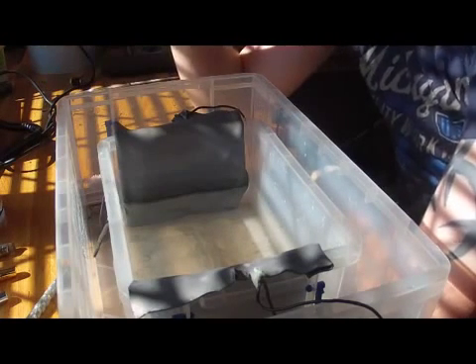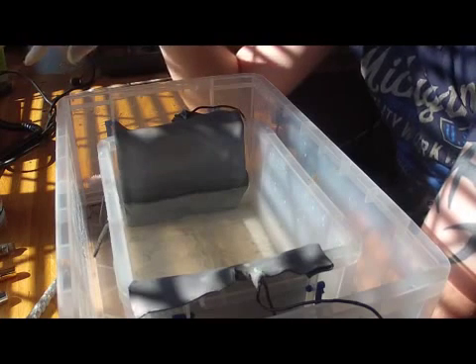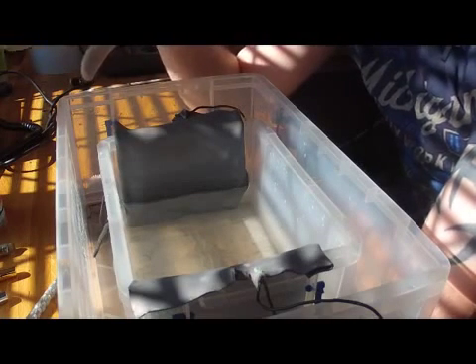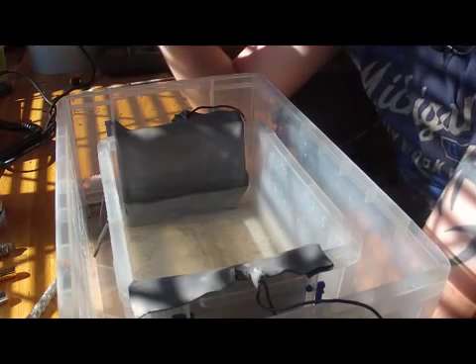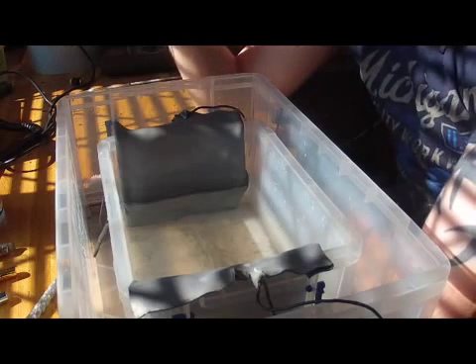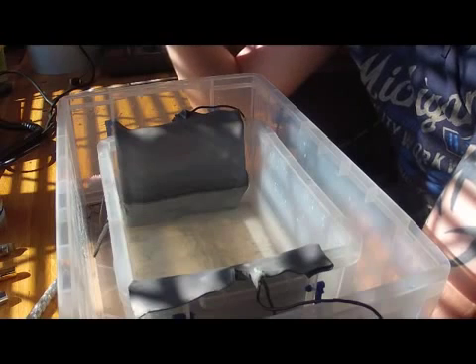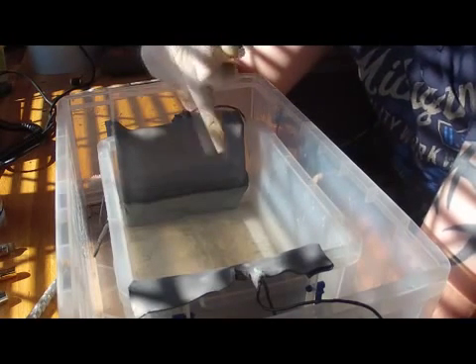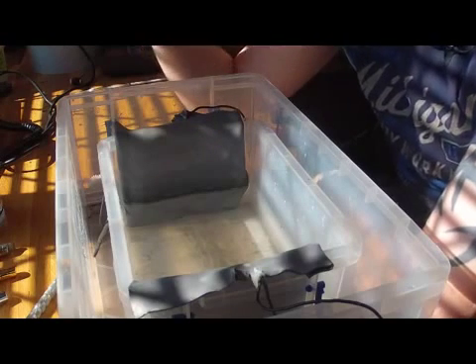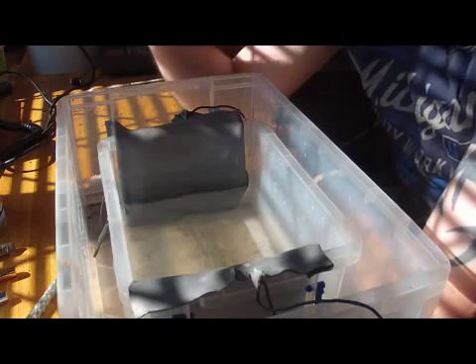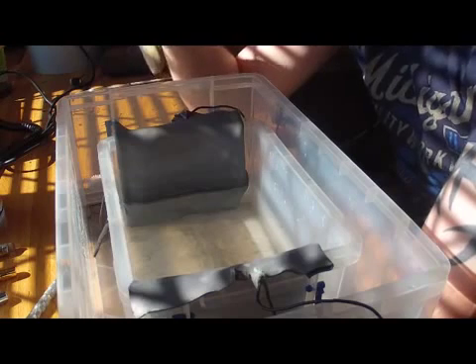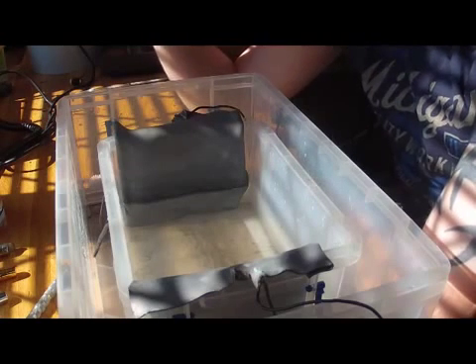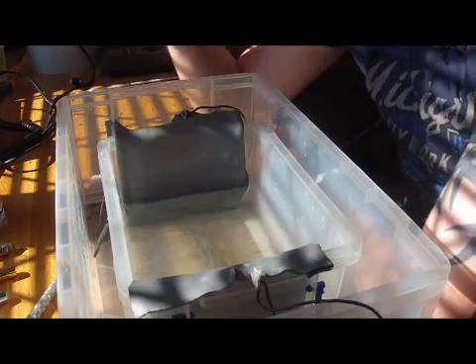Now I can tell you now that the surface area of the pieces I'm going to be anodizing today adds up to roughly six inches square. Don't forget that if the anodizing liquid, the electrolyte, can actually get inside the part, we're also anodizing the inside of the tubes as well. So we have to take that into consideration when working out the surface areas.